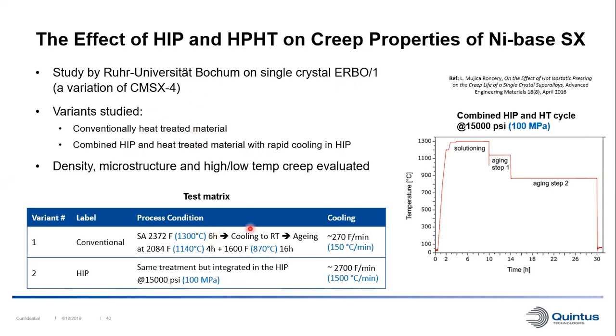So here we can see the parameters for the conventional heat treatment. We have a solution annealing for 6 hours, then we cool down to room temperature, and then there's an aging first at the higher temperature for 4 hours, and then at the second temperature for 16 hours. And the cooling rate that was achieved in this gas quenching vacuum furnace was around 270 Fahrenheit per minute.